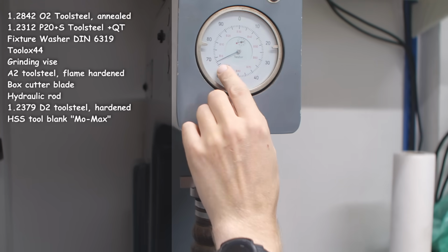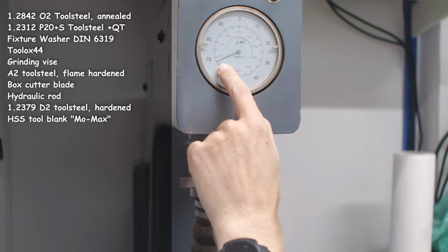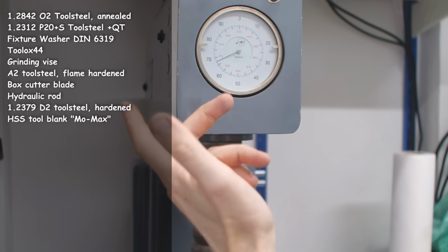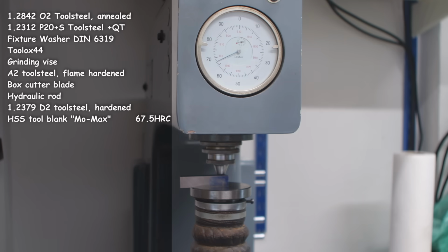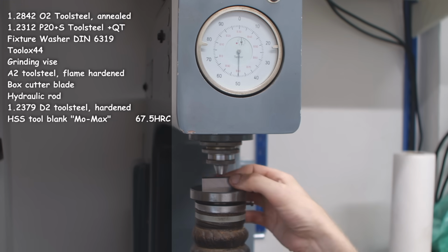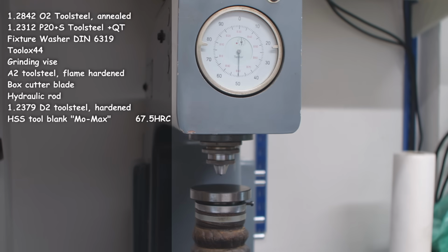And we get 67 and a little bit, so 67.5 Rockwell C. That's what I would expect of high-speed steel. That's hard. That's really, really hard. If you try to touch this with a file, you will damage the file.